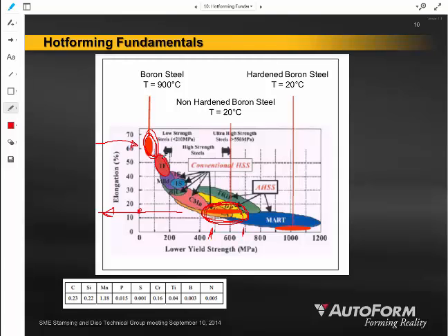But what's really cool about this idea of hot forming these specific grades of boron steels is that when you cool and quench that material, the material ends up in many cases significantly stronger than it was even coming out of the mill. Now that's not true for every other grade of steel that you might think of, right? You can't do this trick of hot forming the material with plain 1008 1010 steel.